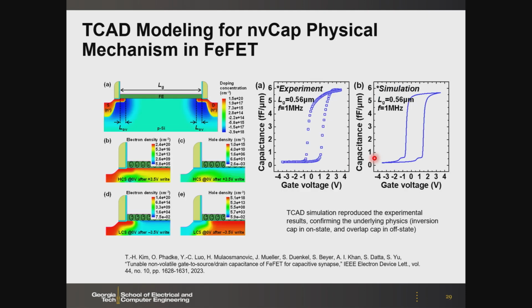And then we went on from the TCAD modeling point of view. We also verified the working mechanism, and we can reproduce the CV from the TCAD simulation. And you see that this agrees with experiment. We can look at the electron density and look at the inversion and accumulation depletion mode, and then we measure the CV, then that will match what we proposed.